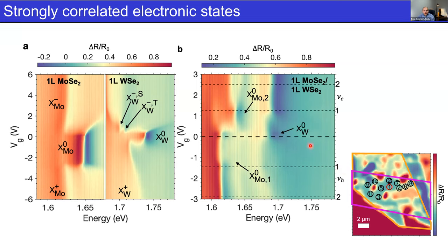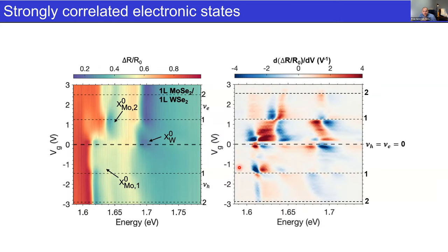And similarly here, we see these strong oscillations, and we can better visualize these changes with gate voltage by taking a derivative with respect to the voltage. And so this is the plot on the right. It's the same data, just plotted with the derivative with respect to the gate voltage. And so we can see here that we have highlighted the one or two holes per site, or one or two electrons per site. And we see these drastic changes in this differential reflectivity map at these biases. And this corresponds to what we can work out for the basic carrier density in terms of the number of carriers per Moiré site. So that works quite well. And we can actually use this as a way to diagnose the twist angle as we look around our sample. And for the most part, it's 3 degrees plus or minus about 0.2 degrees.